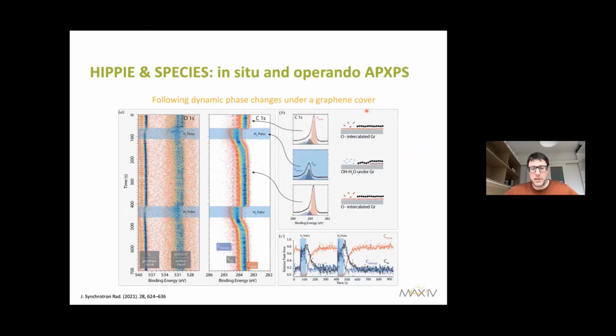We have two types of gas pulses, the oxygen-rich and hydrogen-rich. Once you pulse the gas, one after the other, you can see a change in the chemical composition on the covered graphene or undercovered graphene on the bare sample. And then you can do the time series. You can fit, you can plot it versus time, you can define the time constants as shown on the right-hand side graph. So you can correlate the gas phase composition, or the composition of the reagents, with what's going on in the chemistry, that is, the catalyst itself.